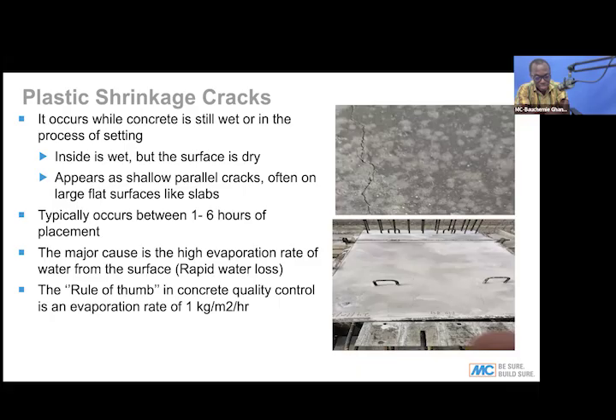So that creates a differential between the surface and the concrete itself. Now, when this happens, because the loss of water on the surface is very high, the drying process on the surface becomes faster. When it dries faster, the surface becomes hard. So by the time the rest of the concrete begins to set and shrink a little, it causes a pull on the surface that causes some cracks.